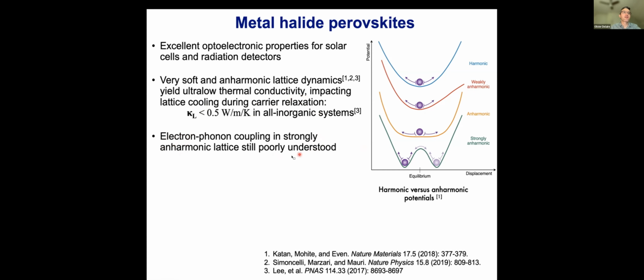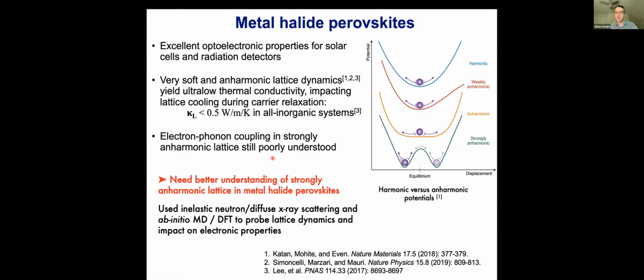coupling and the photocarrier relaxation with the lattice. But we don't have an electron phonon theory that's currently able to describe coupling of electrons with excitations that are not well-defined phonons. So there's actually a lot of developments in this area, but we need to start by better understanding the phonons in this kind of very anharmonic potential illustrated in this cartoon at the right here.